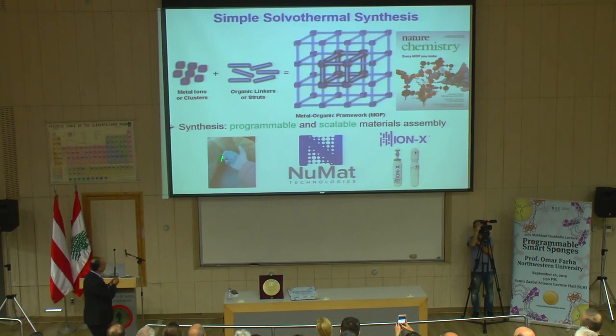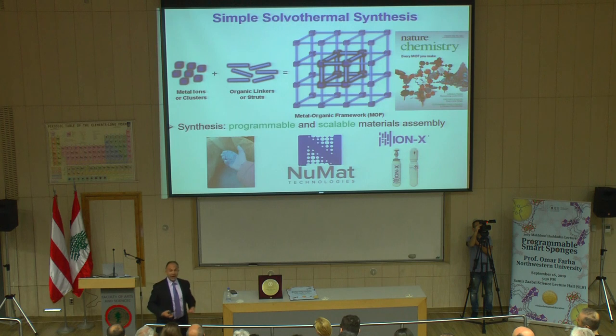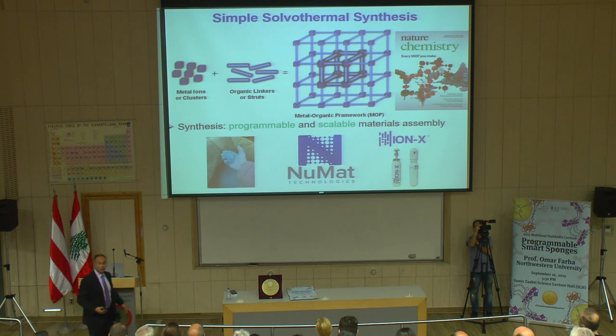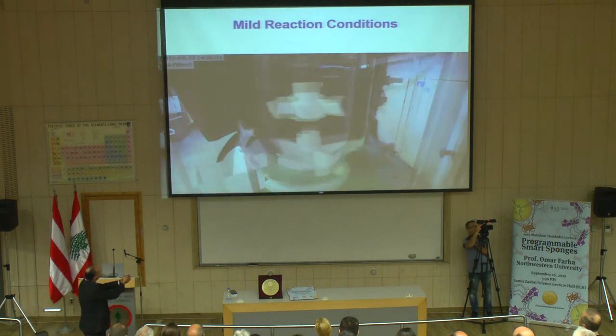And my company, we make them at about half a metric ton a batch. So we're not talking about a few milligrams. We start with a few milligrams in my lab, but it can be scaled to almost half a metric ton, and soonish it will be about a metric ton per batch. So this is what I'm showing here, about an 8-hour reaction.